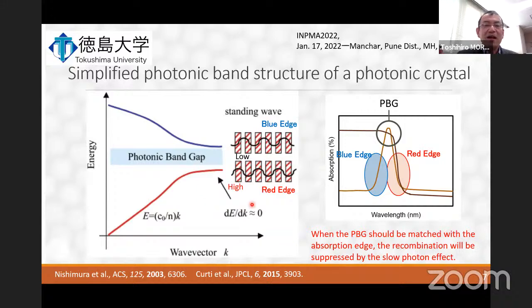The photonic crystal. At photon energy approaching from the left side, the group velocity of light decreases, and light can be increasingly described as a sinusoidal standing wave that has its highest amplitude in a high refractive index material site. The high refractive index part of the structure has the highest amplitude of the standing wave.